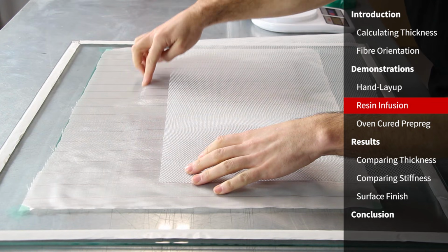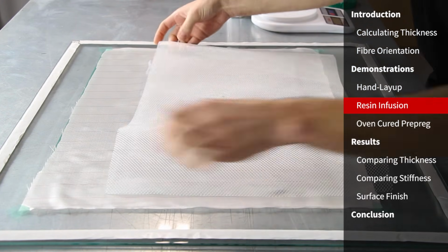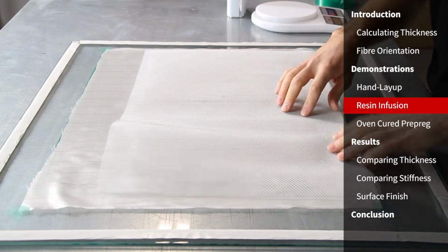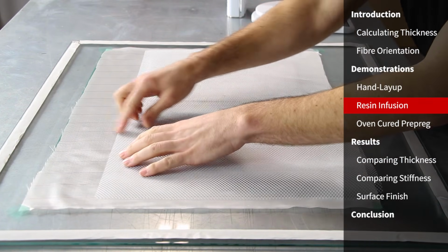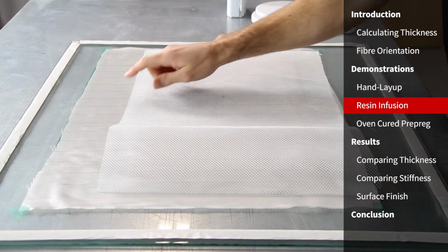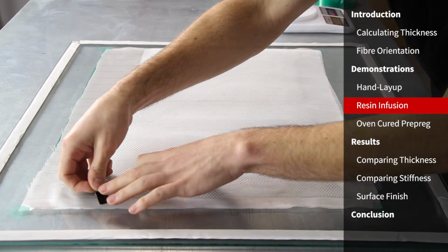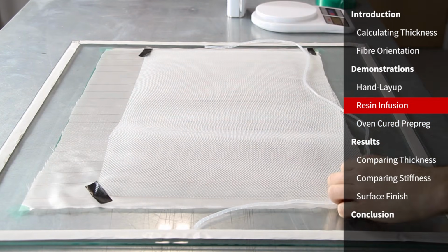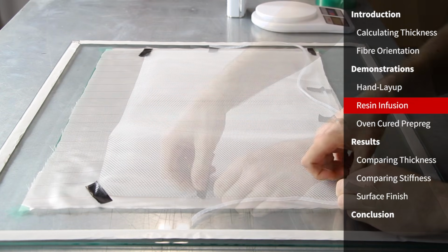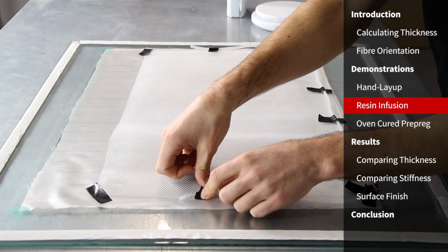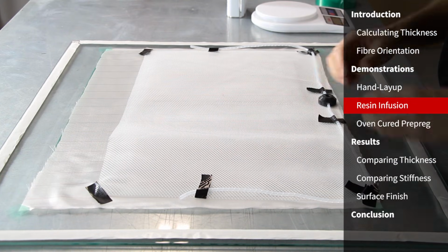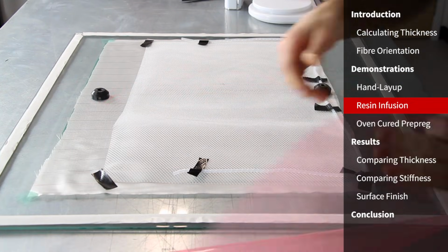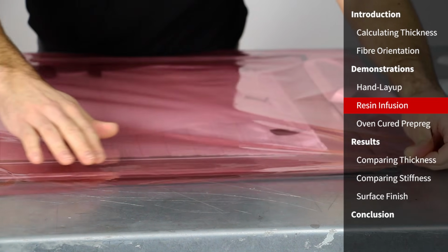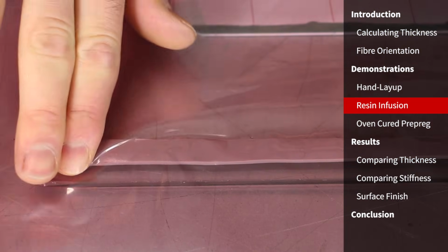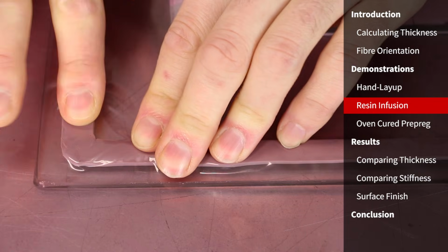The first, you can see where the laminate ends here on this sheet. Now what we want to do is set up a resin break. So the infusion mesh is going to facilitate the flow of the resin through the laminate, but we've got this area at the top where we have peel ply with no infusion mesh, and we're calling that a resin break. And the idea of that is just to slow down or practically halt the flow of the resin through the laminate when it reaches the area of peel ply where there's no mesh, and that gives us plenty of opportunity for far corners of the sheet to get fully infused before the resin starts being drawn down the vacuum line. And of course, as ever, it's essential to make sure that this bag is really well and truly sealed.